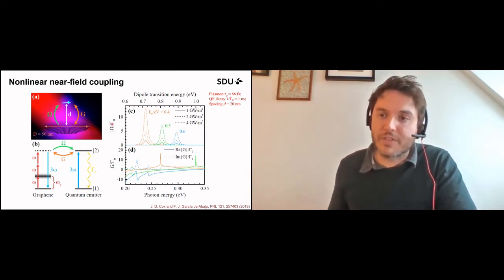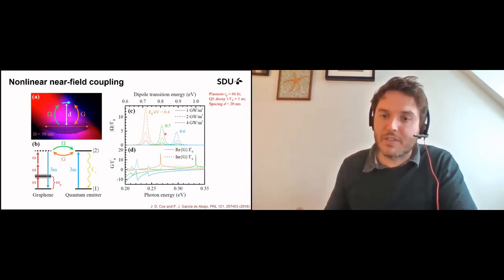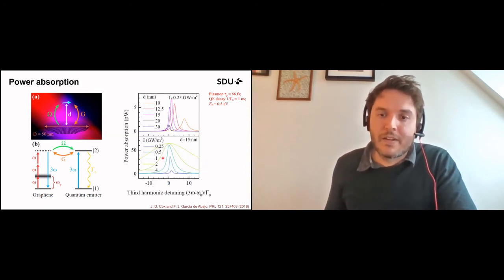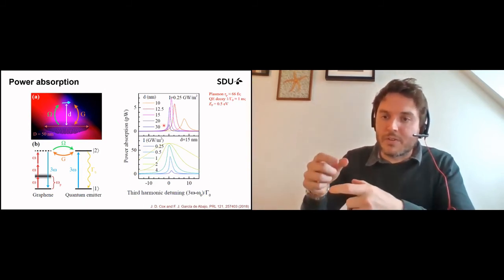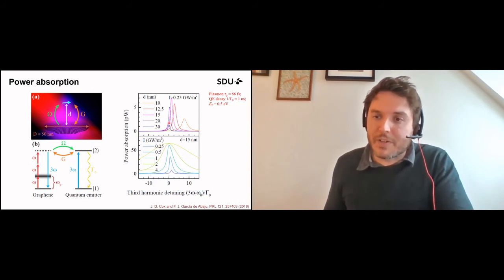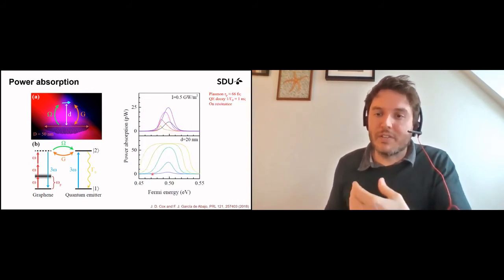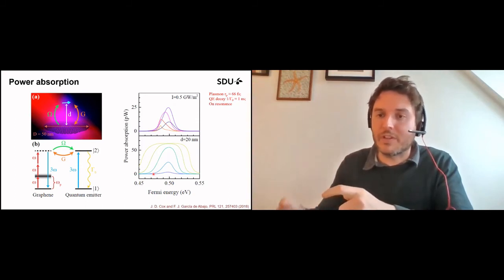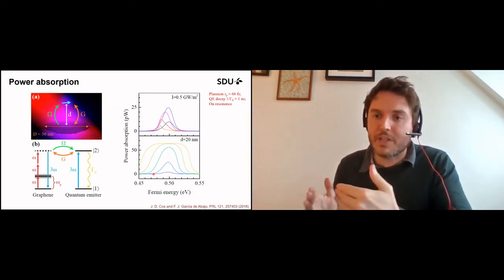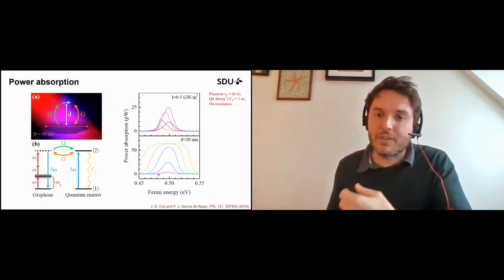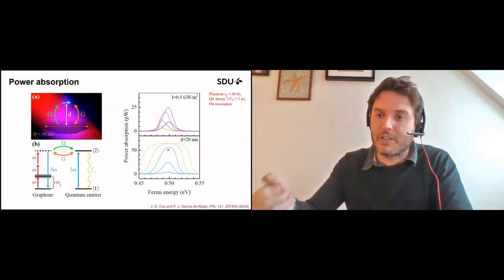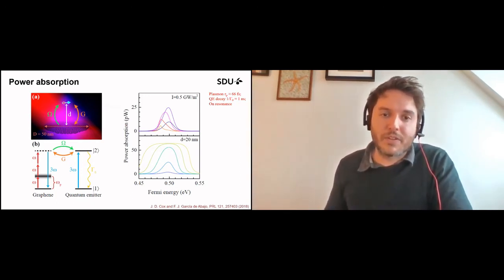So in this proposal here, I'm showing, for example, the Rabi frequencies that you would see if you were illuminating this hybrid system with a monochromatic laser field. This would be the characteristic frequency of the excitation in the emitter. And by changing the Fermi energy in graphene, you can change how that happens, the strength of the interaction, also the frequency. So, of course, if you move the emitter closer or further away from the graphene island, you can tune that response. But what's more interesting is if you just leave the emitter and the island alone, except you electrically gate the island, and then you can electrically tune the plasmon resonance and change the interaction of the island with the emitter. Right, so this gives you essentially an electrical knob you can use to tune the properties of the quantum emitter and therefore the light that it might be emitting or absorbing.